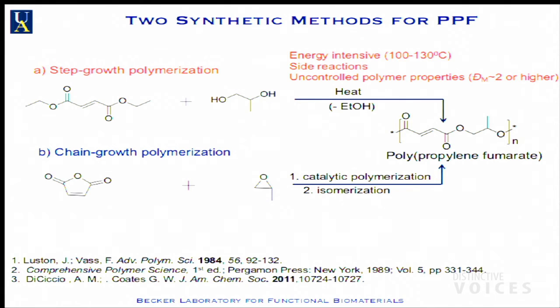Now, this is diethyl fumarate, very expensive, okay? Propylene glycol, you can condense this under high energy conditions. You drive off ethanol, it generates a lot of heat, and you get very uncontrolled polymer properties. So small molecular weight chains, intermediate, large, it's a mess at low molecular weight. And that's why, even if this cured cancer, you couldn't manufacture it this way at 3,000 Daltons, because in consistent manufacturing, good, or what's called GMP processing, it just doesn't work.